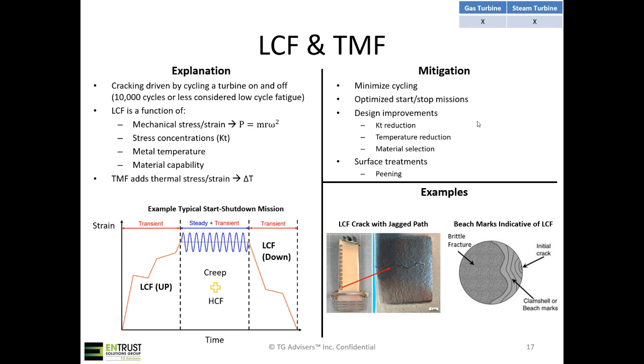Ways to really minimize the effect of LCF is to cut down on your cycling, your starts and stops. Usually base loaded units will be less worried about LCF than peakers, for example. You can also optimize your start and stop missions to make them a little more gradual and have more even heating and cooling. From a design standpoint, you can reduce your Kts, you can reduce your temperatures, or you can improve your materials. There are also other things you can do, such as peening, that will improve your robustness to LCF, but it won't necessarily eliminate it.